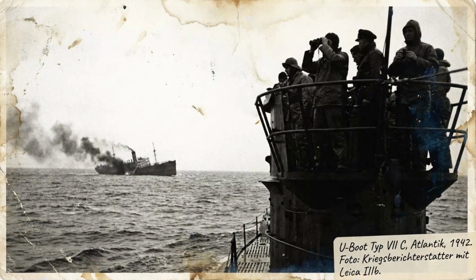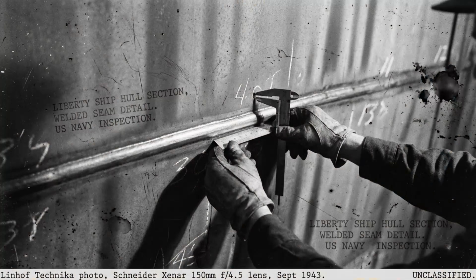The welded hulls were particularly impressive. German naval architects had been skeptical of welding for hull construction, preferring the traditional riveted method that allowed ships to flex and absorb stress without catastrophic failure. A riveted hull was essentially a collection of overlapping plates, each one somewhat independent of its neighbors. If a crack developed in one plate, it would stop at the edge of that plate, prevented from spreading by the physical gap where the rivets joined the next section. A welded hull offered no such protection. A crack in a welded structure could theoretically propagate through the entire length of the ship without interruption.